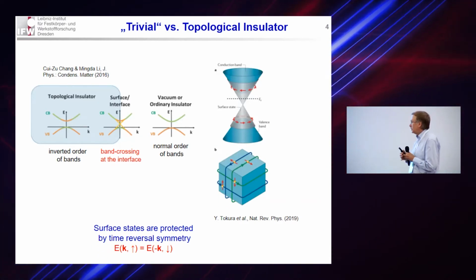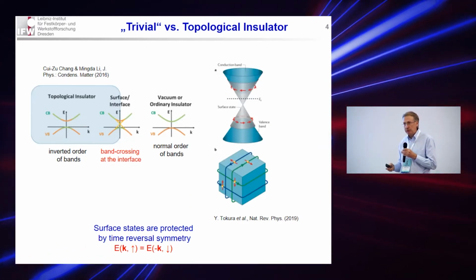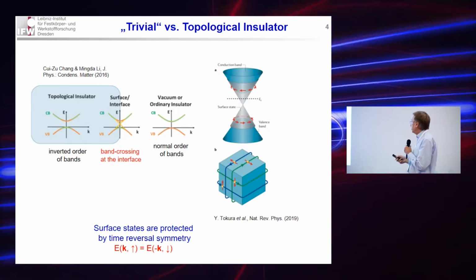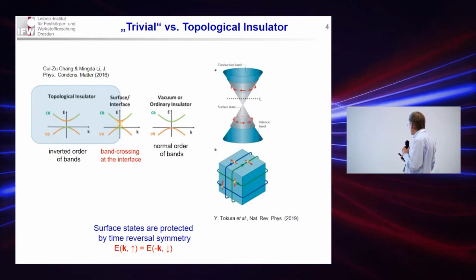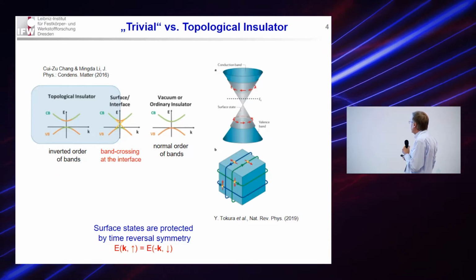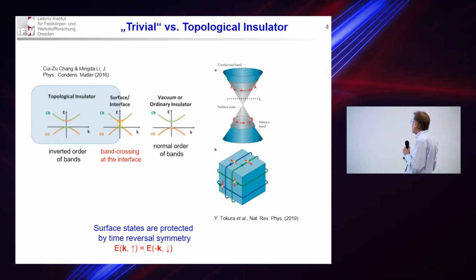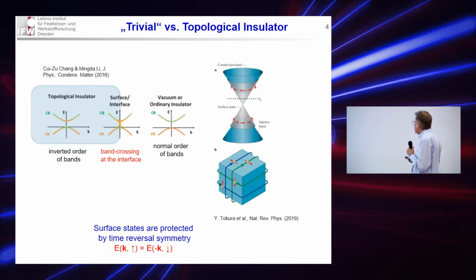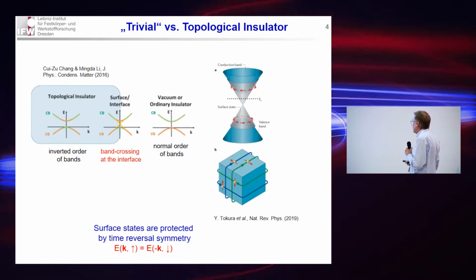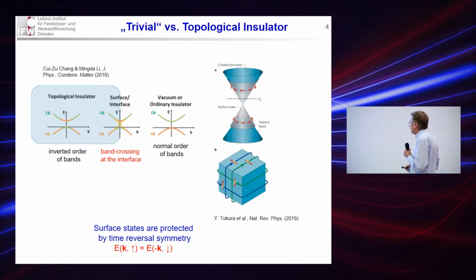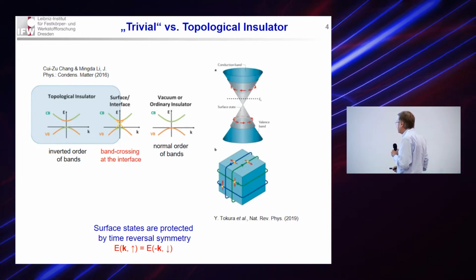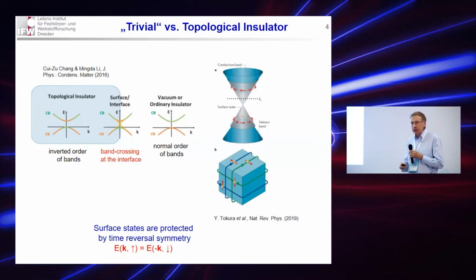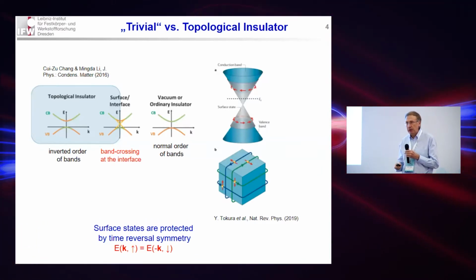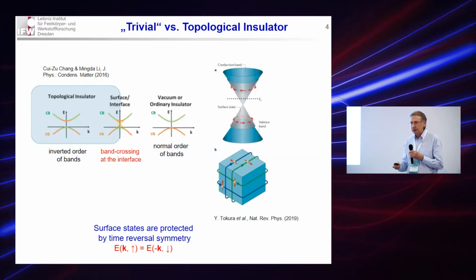And that has important implications for the transport properties, because in this material, for instance in the topological insulator, there are these spin polarized currents on all surfaces, protected by time reversal symmetry. But that transport is, for this reason, practically without dissipation. It's kind of ballistic transport.